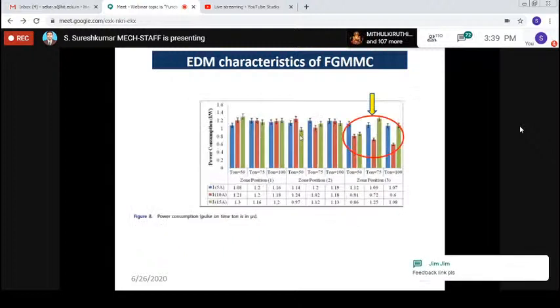And again, on the same ideology, overcut was measured with the EDM process. Again, the same trend is noticed for zone 3. Again, in zone 1, where the rich mixture is available, the overcut formed is less. In terms of power consumption, I think these are the only authors who have reported the power consumption during the machining process, measured in watts. It was reported that for region 3, the power consumed for machining such a zone is less compared to the other two regions.